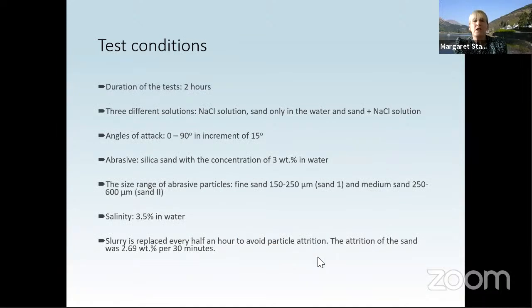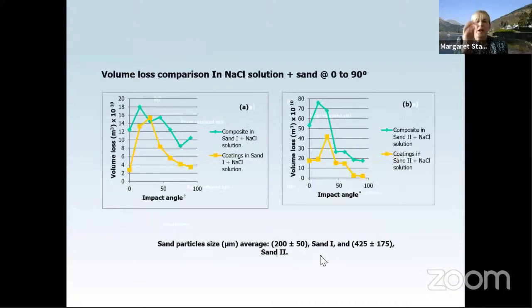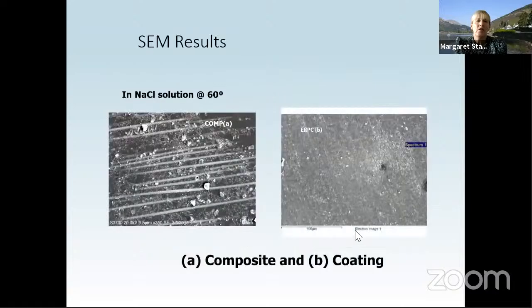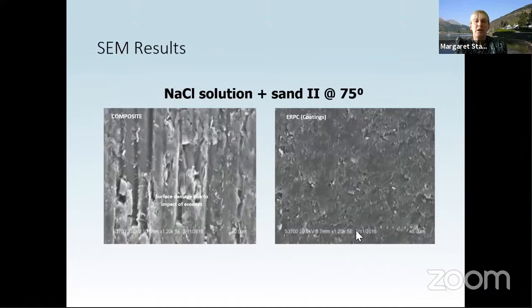So I just want to give you some results. What we found was that if we looked at two different sand grades, we found differences in the effective impact angle for the composite and the coating. So of course, not surprisingly, we get much higher erosion rates with our larger particles. Okay, so these are some SEM images of the surface micrographs.